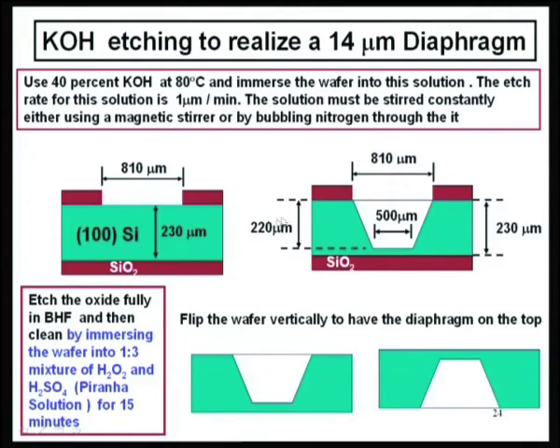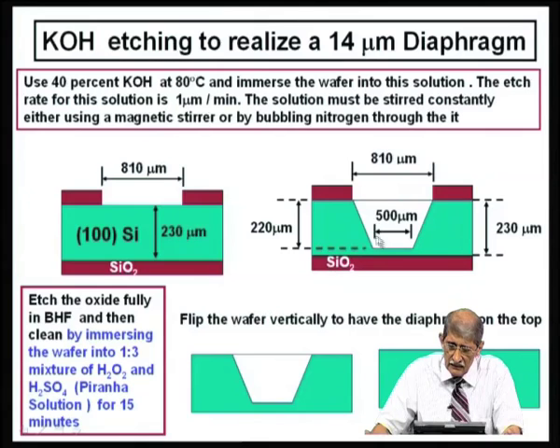If you etch up to 220 microns, and the size left out here is 500 microns, then when you etch 220 microns, you can calculate that the size of this opening here is 500 plus 220 divided by 0.7, that is 810 microns. So in the design, in the pattern, you must design an 810 micron pattern size. When you have that pattern opened, when you etch it to a depth of 220 microns,